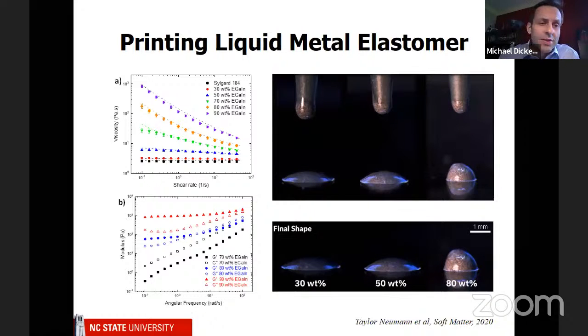And so when you want to print some of these inks, what you want to look for is a couple of things. One is you want to look at the viscosity as a function of shear rate. So when you push an ink through a nozzle, you get high shear rates. And so you want something that actually gets easier to flow as you push it. So this is called shear thinning. And you can see that this black data, which is just the silicone, is constant with respect to shear. So shear is like this. It's basically applying a shear stress to the material.